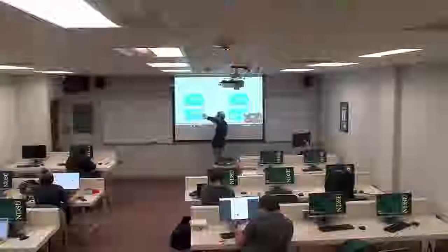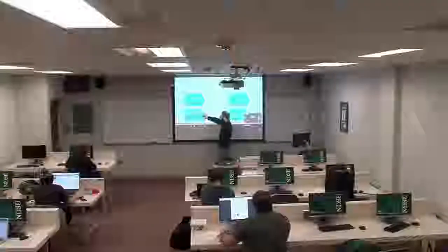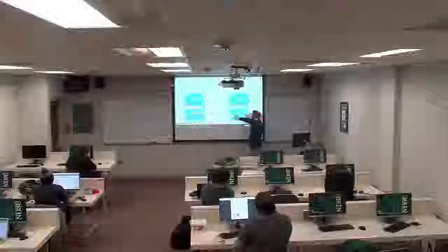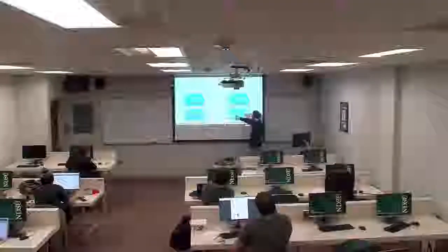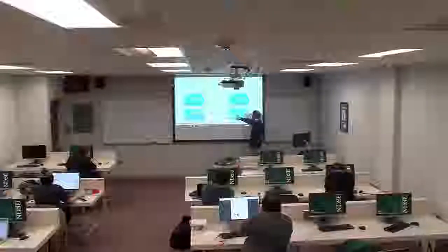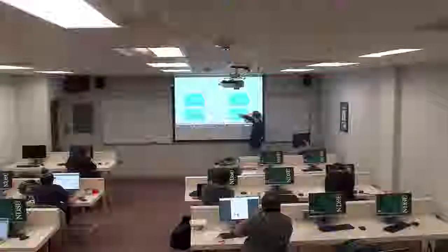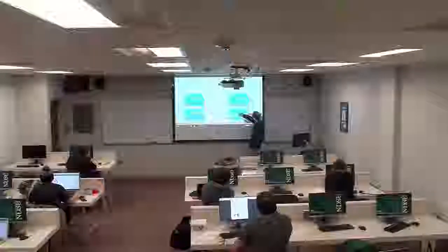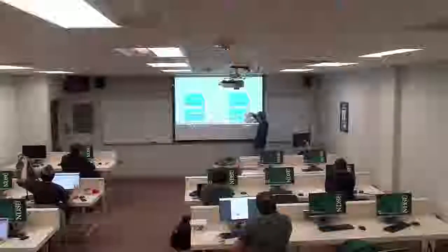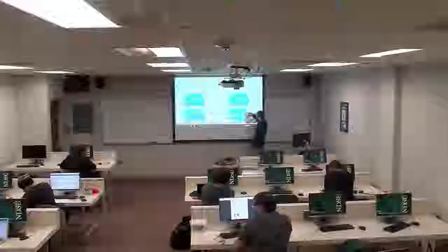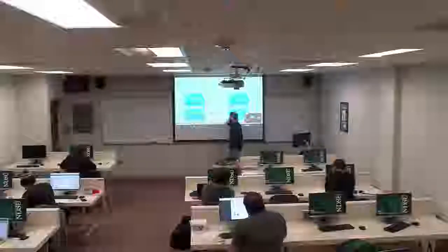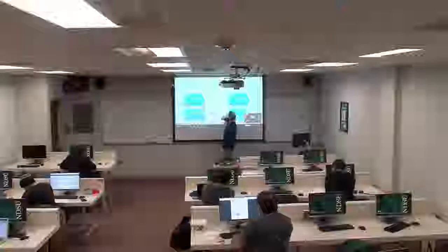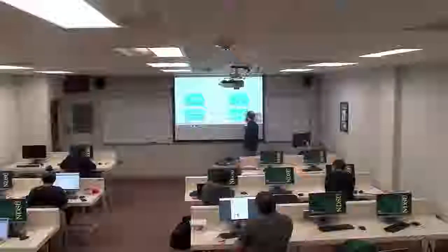So this actually is a charge transfer state in this case, whereas in the anatase model, you have a very scattered charge distribution here. You get a slight backwards charge transition from what we're looking for in this device, and then both excited charges end up on the titanium dioxide as the system relaxes. And these were both chosen to be the transitions that had the highest oscillator strength for both of these.